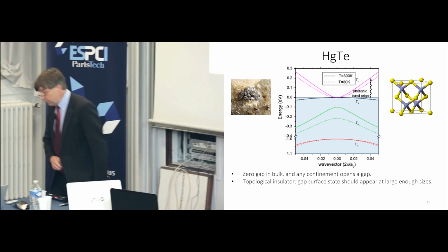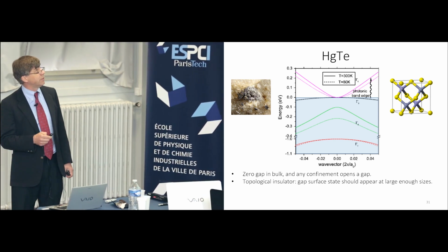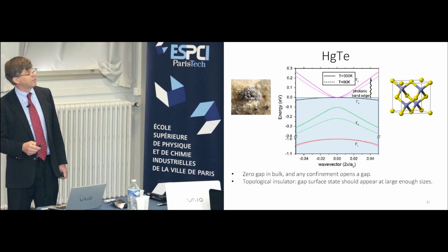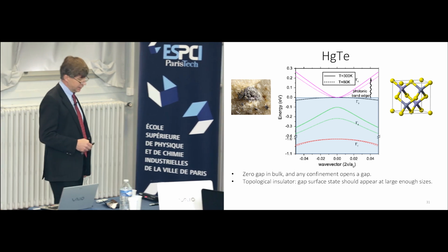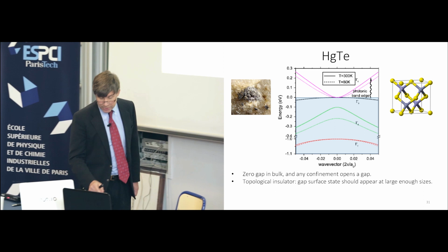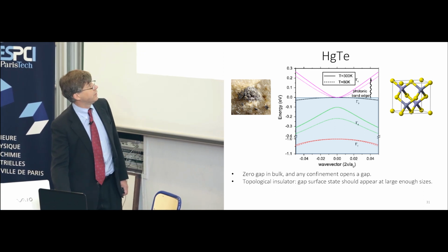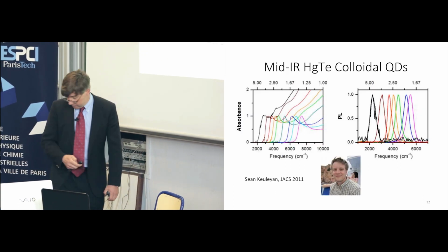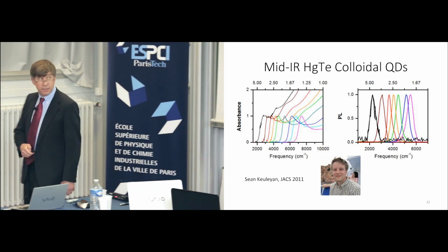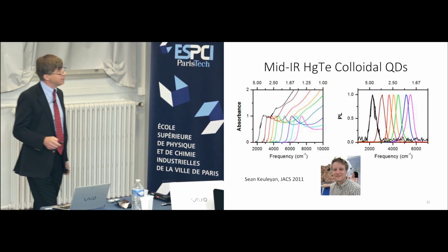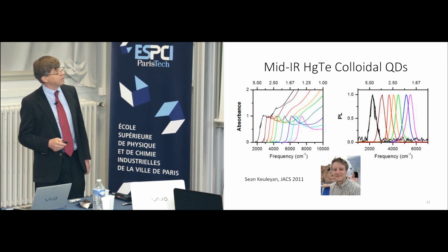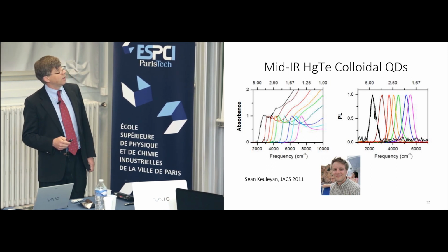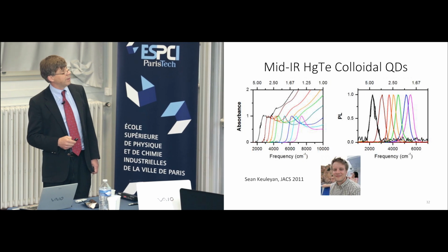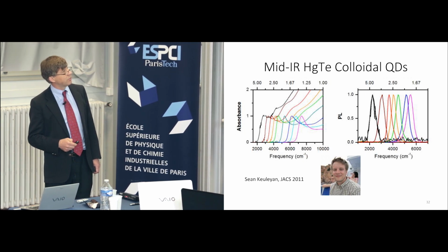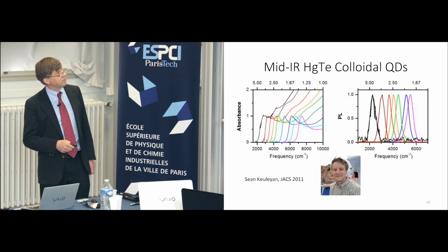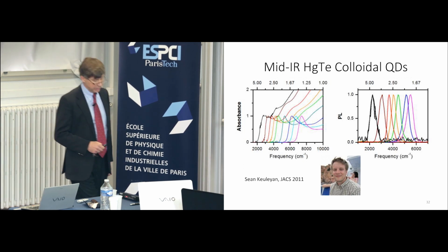So looking at mercury telluride, it's a zero band gap. It has a simple band structure. The electron has this nice dispersion. Seemed really ideal, but you never know when you make a quantum dot if the surface is going to screw up things. So I had one brave student, Sean Keuleyan, who decided to work on the mercury compound. And he developed a synthesis that was better than before, which allowed him to get this wide range of tuning in the mid-infrared, covering fully the 3 to 5 micron range with fluorescence as well.